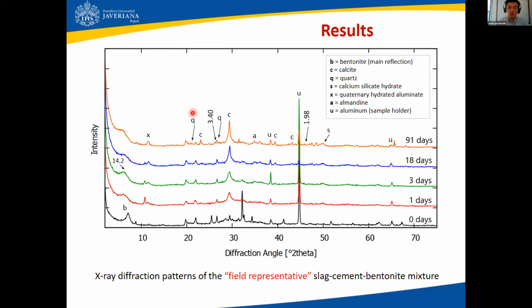And second, the Q peak, which is quartz. Interestingly, in real field applications, when the slurry wall is being constructed, a lot of sand or perhaps other soils gets into the mixture and gets into the trench, actually, just as a contamination, if you will, as a cross-contamination material or soil from the construction process. However, for this particular study, we did not intentionally add sand or other soil, just to prevent misinterpretation of the data. However, you still can see a very tiny little peak of quartz here that is going to be remaining in most of the X-ray diffraction patterns.